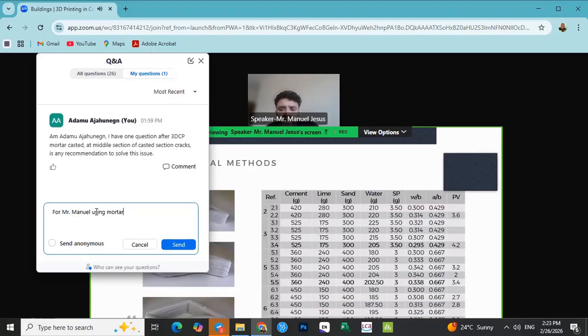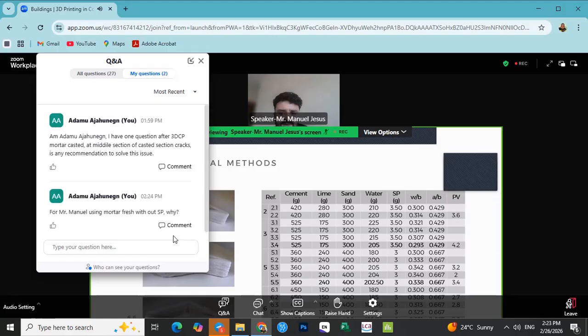The best performing formulations were then selected for printing trials, this time with superplasticizer. And here, the primary objective was to enhance workability and flowability, but without increasing the water to binder ratio. Despite these optimization attempts, some formulations with higher lime content proved unsuitable and therefore were excluded. The resulting water to binder ratio for these mortars ranged between 0.29 and 0.34, and once again they were consistent with the established literature.